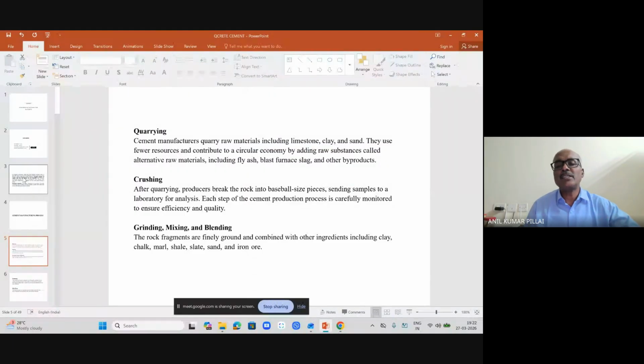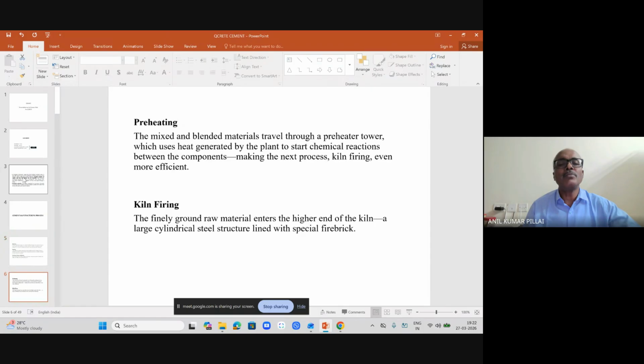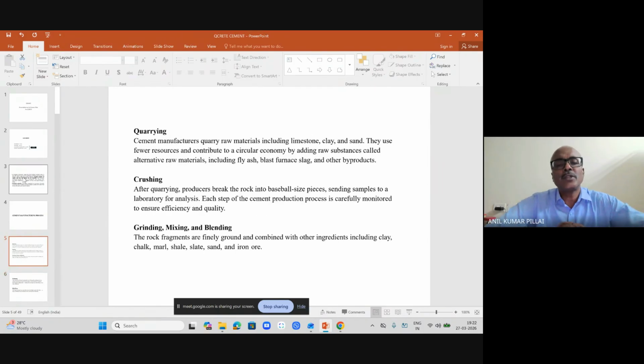What is important is, if you want to manufacture a cement of consistent quality, the variations right from the raw materials should be evened out, and all-out measures should be there to ensure that the blending is being done. We have different mechanisms for that, like the CF silo and the stacker reclaimer, which ensure that the standard deviation of the raw material is brought down. Because the challenge is to manufacture a cement with minimum variation.